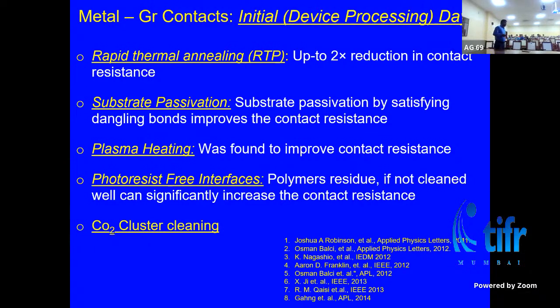In the beginning, when 2D materials were discovered, people tried the conventional methods on the new material system. They heated up the system, did certain passivations, did plasma or short time scale heating, cleaned up the photoresist left at the interface, or did carbon dioxide cluster cleaning, to ensure that nothing comes between the metal and the system and to improve the contact. Of course, people reported better contact resistance, but that was relative to a poor interface. You have one side with a better interface, nothing in between, and the other with something in between. It's obvious that nothing in between is going to give you better contact resistance. So that was not a scientific advancement; it's an obvious improvement that you would see.